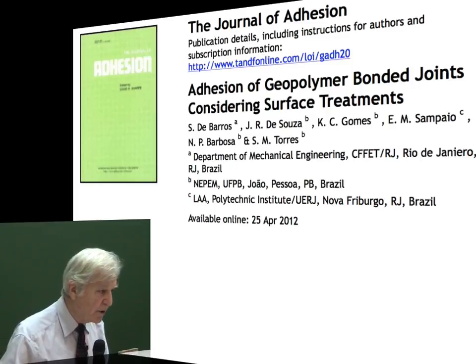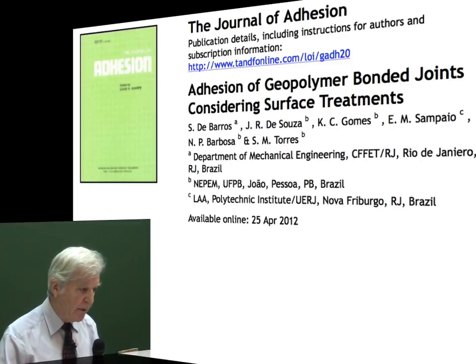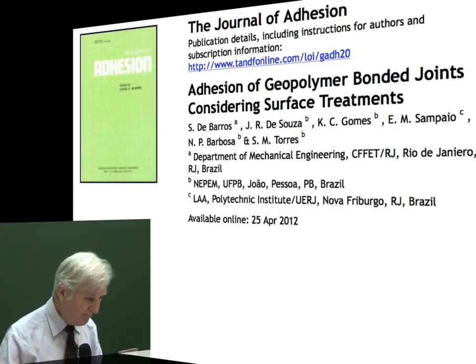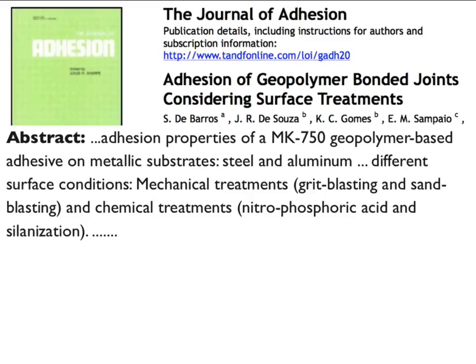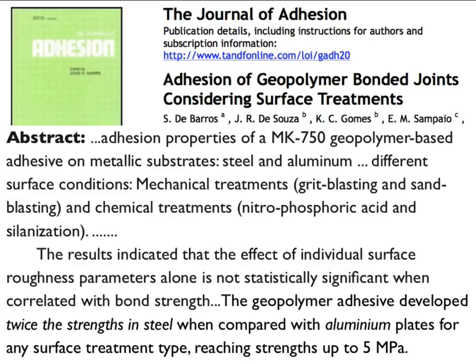And this is here a paper published in the Journal of Adhesion by a team from Brazil, Rio de Janeiro, Brazil, and it says, the abstract, adhesion properties of MK750 geopolymer-based adhesives on metallic substrate, steel and aluminum. These are the substrates that they studied according to different conditions: mechanical treatment, grit blasting, sandblasting, or chemical treatment, nitrophosphoric acid and silanizations. And the result is the effect of the individual surface roughness parameter alone is not statistically significant when correlated with bond strength.